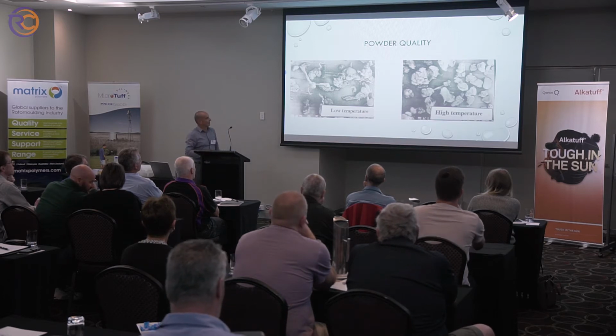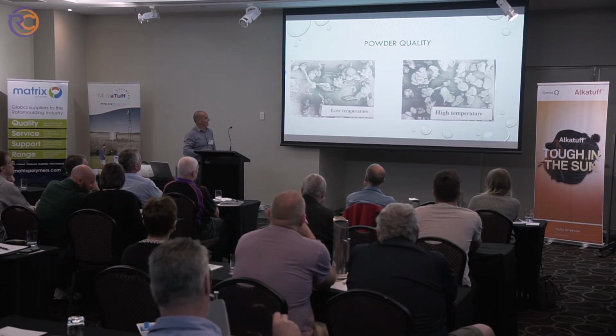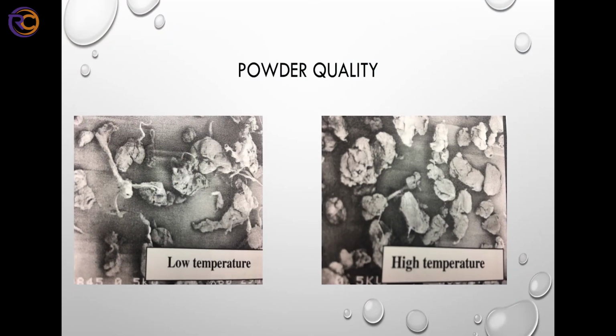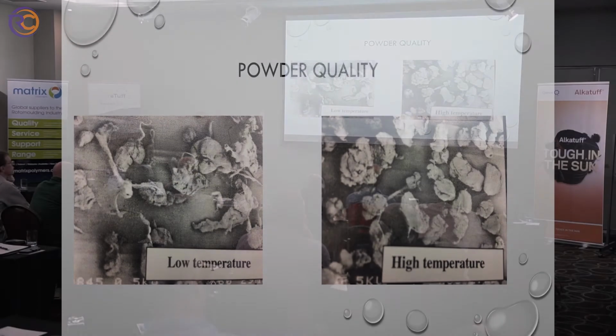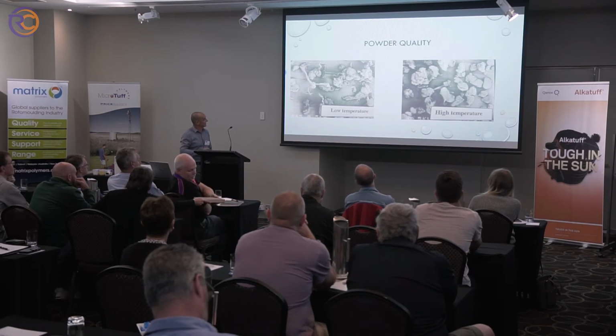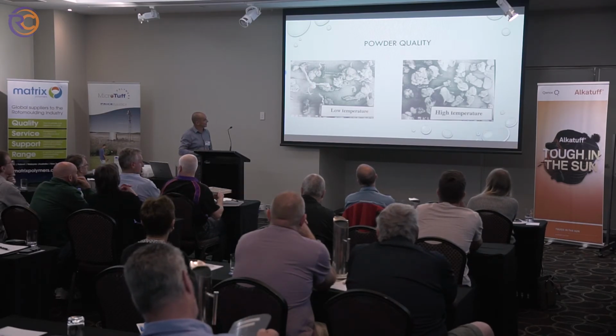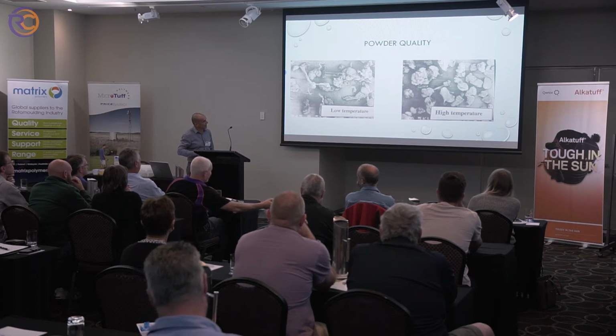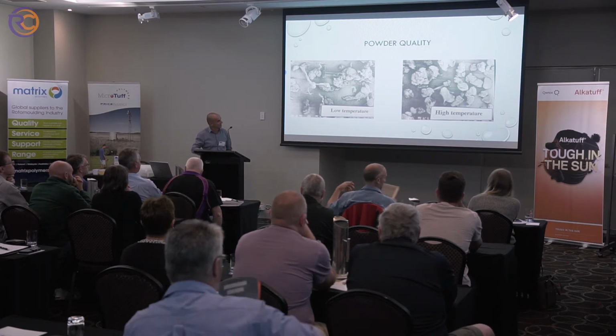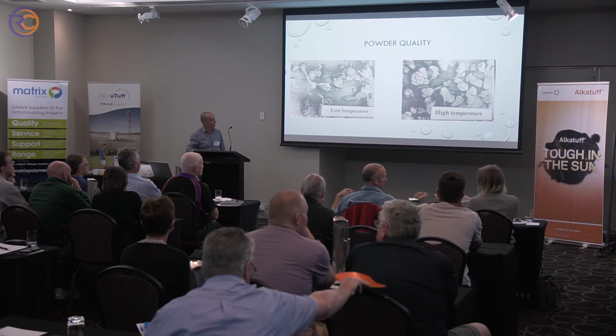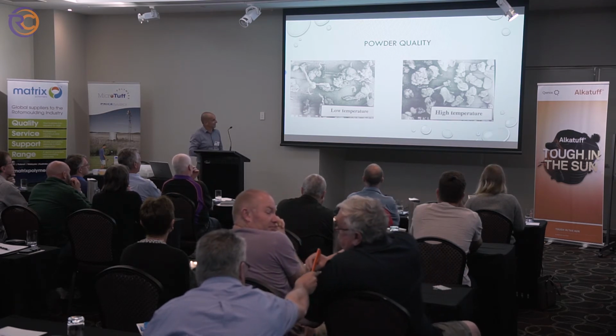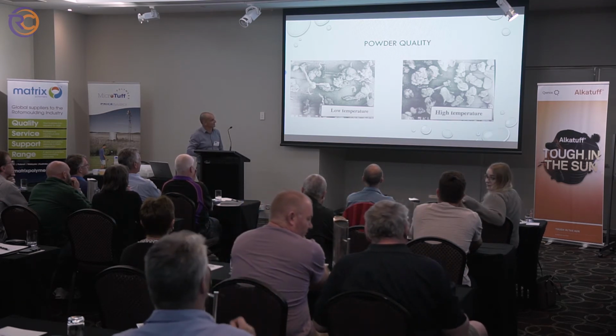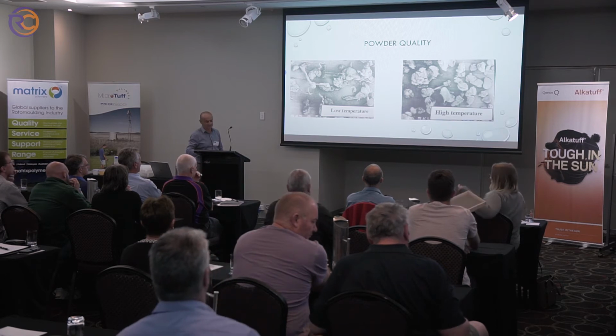So this is a magnified example of powder particles from Roy Crawford's book, and you can see tails on the low temperature material, and on the higher temperature ground material you can see not so many tails, not like ball bearings, but you know, it's a lot. This material is going to flow a lot better than this material.